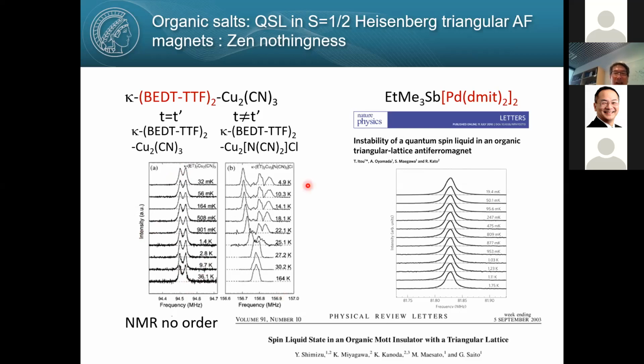But like this compound, okay, this T and T prime is unequal, and so therefore you have strong bond and weak bond. So it's not a triangular lattice anymore. And in that case, with lowering temperature, you can see this line, the distribution of magnetic field, split into many peaks. That means you have a magnetically inhomogeneous environment. That means magnetic ordering. So this you do see magnetic ordering, but this you don't see magnetic ordering down to 30 millikelvin.